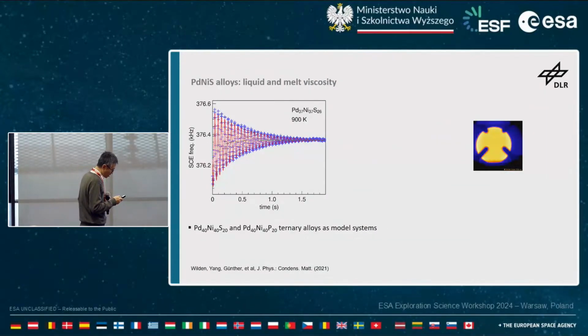Another aspect in this project is to compare the sulfur and phosphorus alloys. This is again measured in the Tempus facility, so the parabolic flight facility, and we do have nice data. This is a colorful image due to the low melting point of the alloy, which is something around 500 degrees C. We have a new camera in the Tempus facility with an infrared spectrum and high speed, which would also be suitable to study solidification if the optical contrast is not good enough.